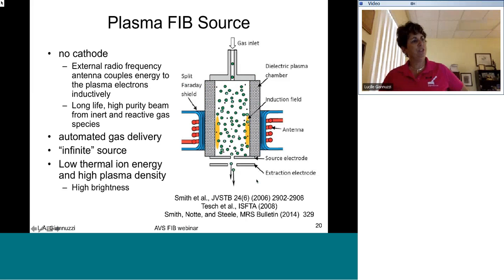However, because you're typically using this at much higher beam currents, you're going to use consumables such as apertures and other things that are going to wear pretty quickly. Again, automated gas delivery. Again, infinite source in the sense that if you have a gas source container, a small little bottle about this big, you will be able to use it for the entire life of the instrument. And it's a very high brightness source, which again allows us to mill things that are much larger with much smaller beams.